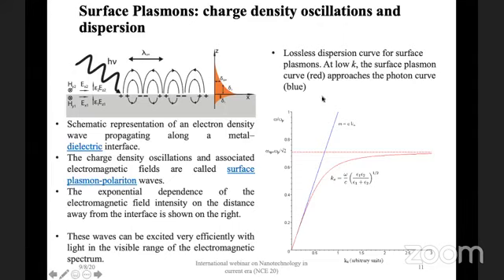On the right side bottom is the dispersion curve of the plasmons. We have this dashed horizontal line, which gives us the bulk plasmon frequency. The blue line is the light dispersion curve given by omega is equal to ck. And then this one over here is the red curve, which is the two-dimensional plasmon dispersion curve. And you can see that it never crosses the light dispersion curve. It's always below the dispersion curve.